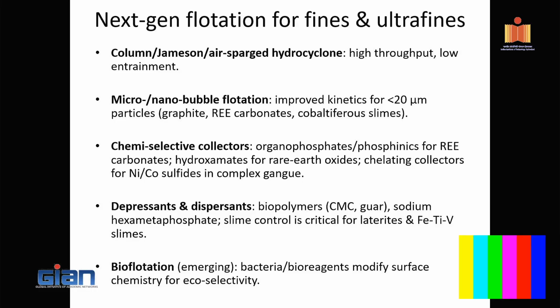but I think we are trying to minimize the turbulence altogether. In a column, what happens? You have a cylindrical section, and then you don't have any stirring or induced turbulence. Rather, you are making the particle and bubble go in a counter-current fashion, so that no turbulence is induced. But that's the concept. If you look at the actual industrial column flotation being operated, of course, operators are always greedy to increase the throughput. So they increase the flow rate, and then they also get some losses. But ideally, you should operate the column flotation not in complete turbulence, but in the laminar to transition region, so that the interaction of the bubble and particle is homogeneous, but not completely heterogeneous. So that's a philosophy one needs to adopt if you are adopting the column.